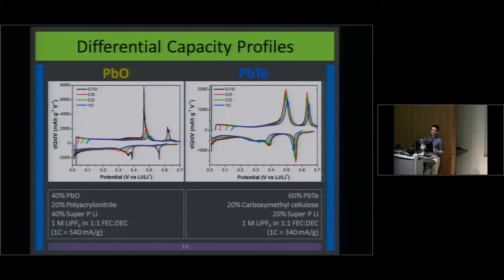So what we want to see is for these 2 peaks to be really close together and to stay close together as you increase your C rate. We can see here for the lead oxide that the peaks shift rightward, or shift wider, rightward on top and leftward on the bottom. But for the lead telluride, there isn't much shifting.